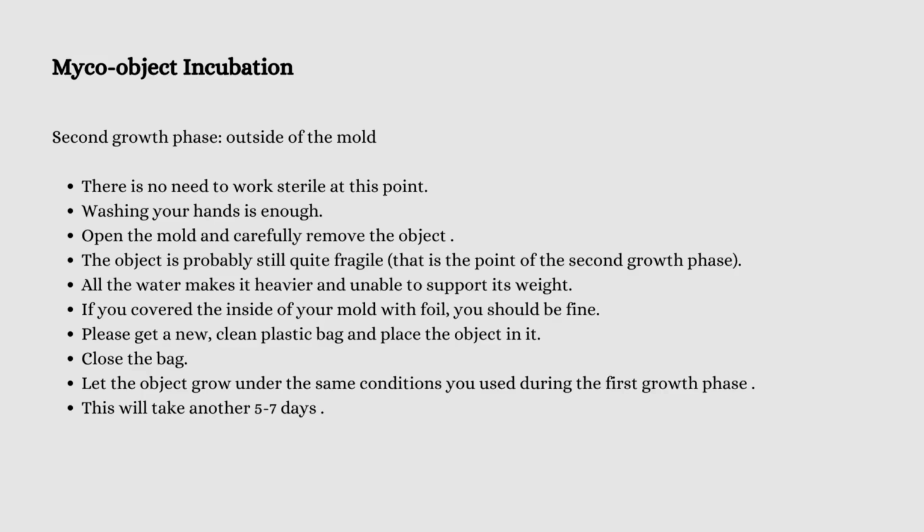And this will take another 5 to 7 days. If it's a really active strain, honestly, even less, like even 3 days. So just have a look at your piece at day 3 and see where it's at and see if you want to stop it there, or if you want to see what happens with another few days under incubation.